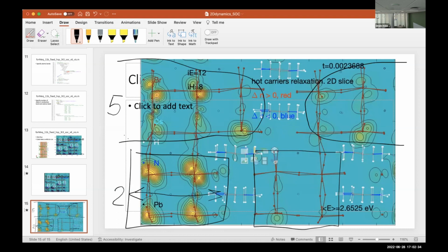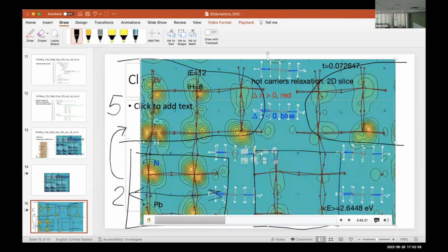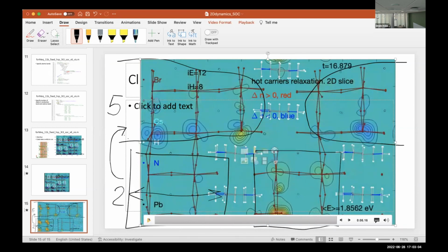The gap in the thinner is bigger than in the thicker. So it is expected that both electron and hole will migrate from more confined to less confined. And if we try to rerun the dynamics, we will see that charge density disappears in this lower segment and will reappear in the upper segment, at least qualitatively. I mean, does it make sense just as an attempt to interpret?